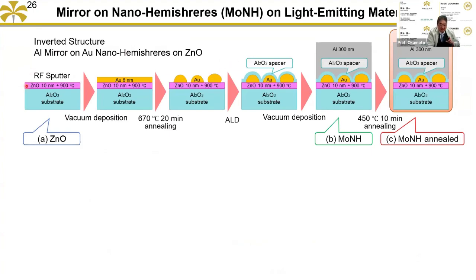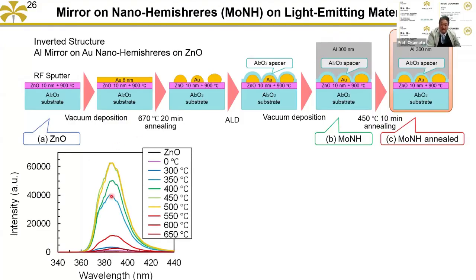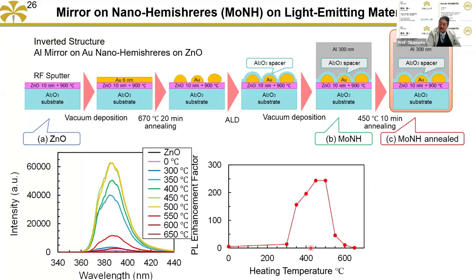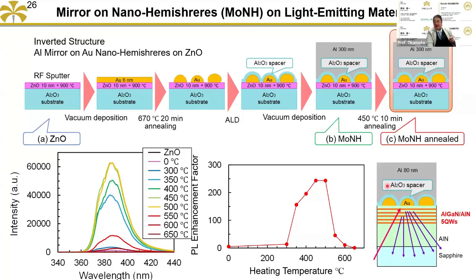Then first we deposit the zinc oxide. Then we fabricate the gold nanoparticle and the spacer and also aluminum there. Then still by using this structure, we obtain the huge enhancement. And the important thing is that after that, one more time, annealing heat treatment is necessary, and we increase the temperature to around 500 degrees C heat treatment. We can obtain 250 times the enhancement. That's very huge enhancement.